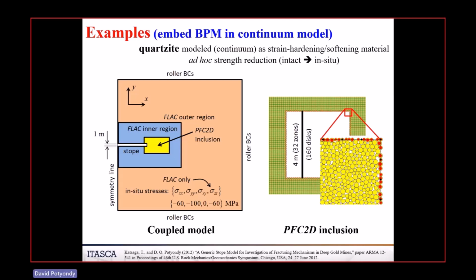This is work where we were modeling, again, a stope in a deep underground mine in South Africa. What we did is we used a PFC region in the tip of the stope, and we had that embedded in a much larger continuum grid. These stresses are very high. You can see that sigma y is 100 MPa, sigma x is 60 MPa.